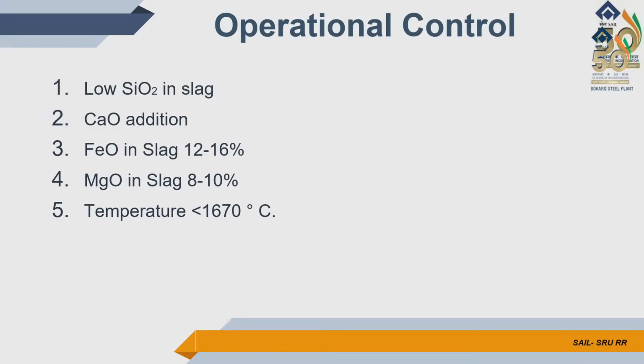During operation, thanks to BSP SMS2, different things were tried. Silica was an issue. Higher silica leads to increase in reactivity with magnesia. So less silica is required in slag. Calcined dolomite addition was done to increase the basicity. Iron oxide in slag was 12 to 16%, but we get 18 to 22% also at different times. Magnesia is also important in slag because if it's not there, then the slag will take magnesia from my brick and brick lining will be reduced.